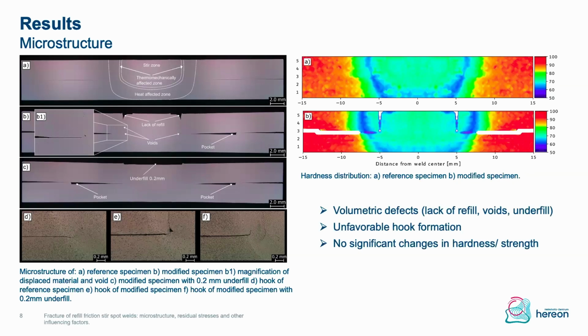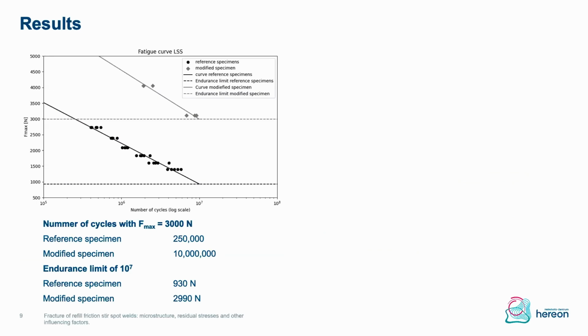So, summarized, in the modified specimen we have volumetric defects such as lack of refill, voids, and underfill. We have an unfavorable hook formation, and we have no significant improvement in hardness and corresponding strength. But what we saw is that we increased the fatigue life significantly.